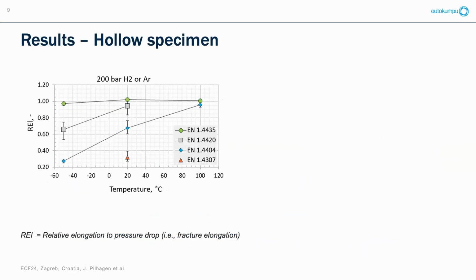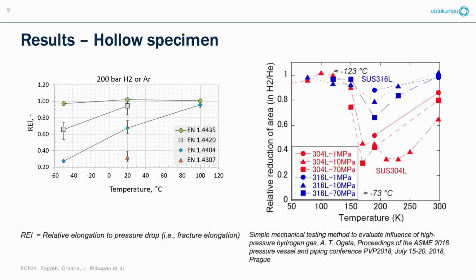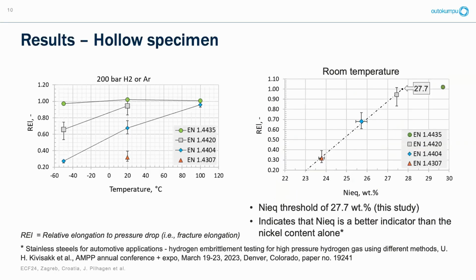And here we have the results. If you look at this relative elongation, and this is the pressure drop. We see that we have an influence of both the testing temperature and the alloying in the steel. And here's a reference to Mr. Ogata, who also tested similar grades at different temperatures. So we can see that the trend lines are similar. If you look at room temperature, we have 4 data points, so we can make a trend line. In this case, you can see that we found a threshold of nickel equivalent 27.7 weight%.